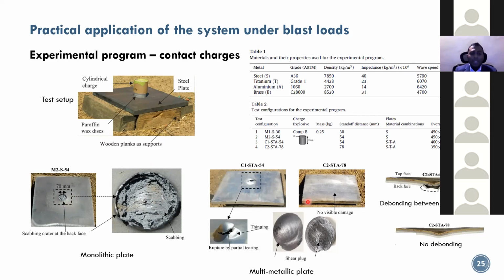But when we combined it in the system with multi-materials, we didn't really see that. We saw a small rupture by sort of shearing, but that was because the aluminium that we used as the back material was slightly weak. So if we actually use a stronger grade of aluminium, we would have been able to prevent the damages, as you can see in the second figure. So if you compare this with what you see here, this new material system has been able to withstand the blast load. It has deformed. Obviously, it deforms. This is where the ductility comes into play. You can see that there's significant deformation. You cannot avoid that, but it does not fail. Now, when it fails, generally when it deals with blast load, it's when the structures fail that we start to get worried.